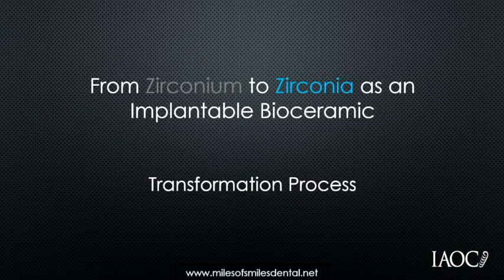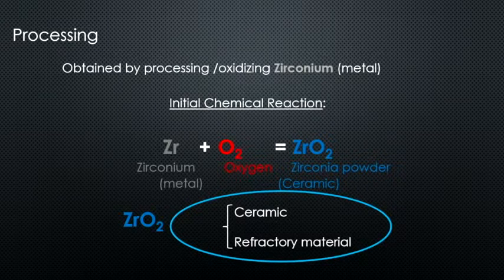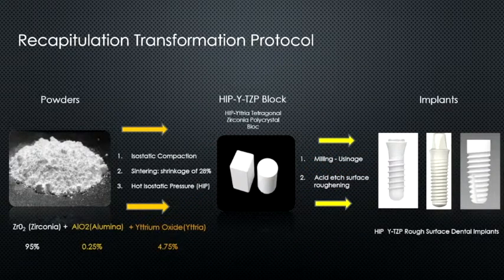So how do we go from zirconium to zirconia? I'm going to go through this a little faster. Again, it's oxygen and zirconium, you get zirconium dioxide, which is also called zirconia. Then, usually, most implants, this is a generic description of how they're made, always start with ceramic powders. These powders are a mixture of three ceramics: zirconia, alumina, and yttria. Yttria is more of a stabilizer. Alumina gives it a little bit of flexural strength, and then zirconia. But zirconia is always in the greatest numbers.